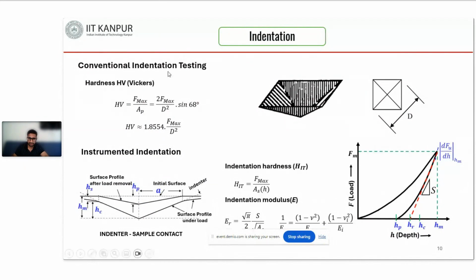So, starting with conventional indentation testing. In indentation testing, we measure the hardness value. Hardness is the resistance to permanent deformation. How does it work? We have an indenter of a particular geometry, and we press the indenter with a static load onto the specimen surface, which is flat, and we hold the indenter on the specimen surface for say 10 to 15 seconds to maintain equilibrium between them, and then remove the indenter.